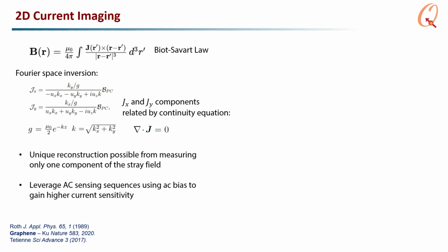Okay, so then we can also image 2D current flows, and this has been perhaps the most fruitful for correlated physics. For 2D current imaging, we try to invert the Biot-Savart law, and that's similarly done in reciprocal space. But in contrast to magnetic imaging of magnetizations, for current flow the reconstruction is one-to-one, completely unique. That's because for 2D current flow there are only two components, and then we also have the continuity equation, which constrains both components. So there's only one independent component.